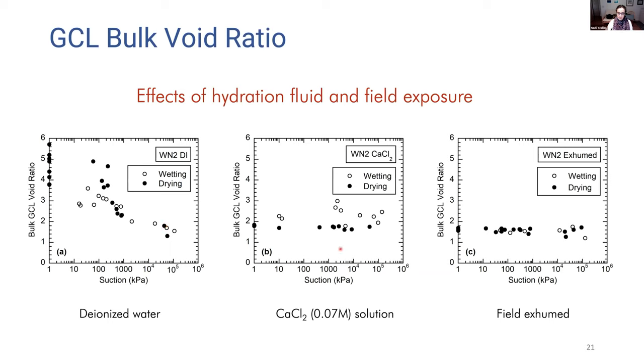For both the calcium chloride solution as well as the field exhumed material, we see that there isn't much difference in the level of the void ratio as a function of suction. For the calcium chloride solution, the bulk void ratio is essentially around 2, with minor differences between wetting and drying paths, and even more uniform and singular data for the field exhumed material, where we have void ratios that are under 2, somewhere between 1.5 and 2 for the entire range of suctions that we applied in the test program. So we see that there are significant differences in the materials as a function of exposure, both to the calcium chloride solution as well as exposure to field conditions.